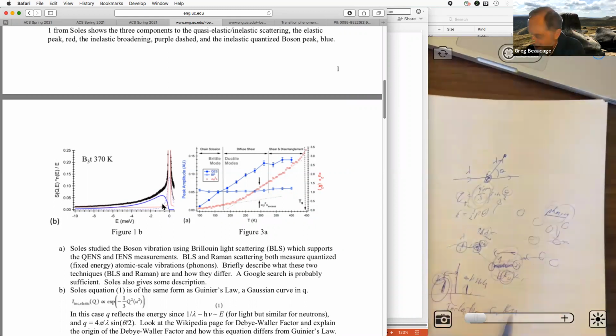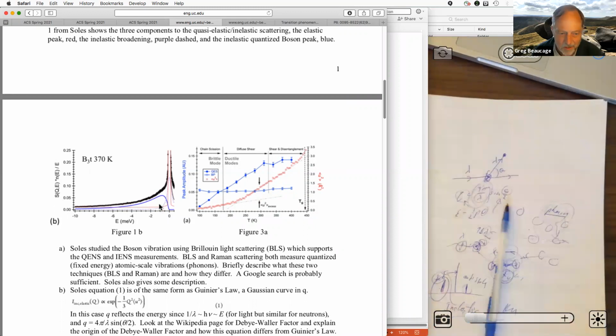So basically you're doing the same thing in Raman and in Brillouin scattering. The difference is the material, what the material is that's absorbing it. So you can put an organic liquid in and it will have Raman peaks, quantized Raman peaks because the bond vibrations are quantized. Or you can put a crystal in and it'll have these phonon peaks. The measurement's the same thing. It's just what you're looking at that is different. And the machines are designed to detect these different kinds of energy absorption phenomena, right? But they're all quantized and they all give rise to basically a peak. It doesn't look like much of a peak, but it's a peak according to what we're talking about here. It's not considered this broadening.